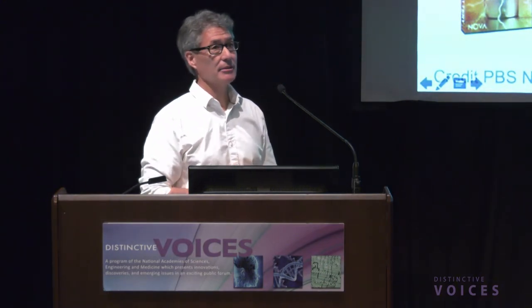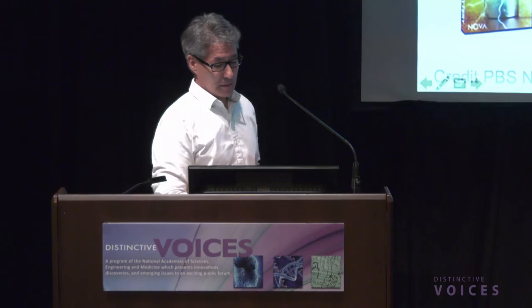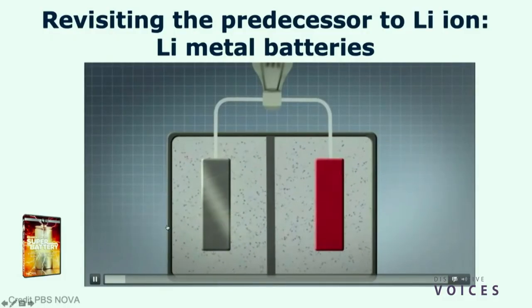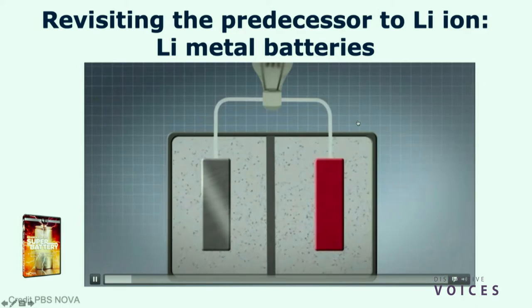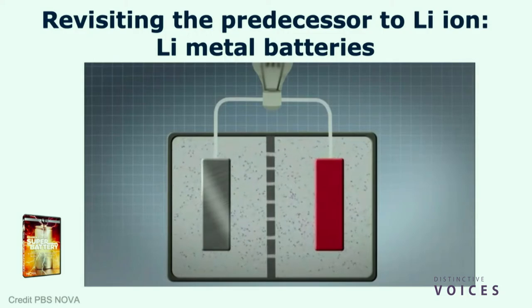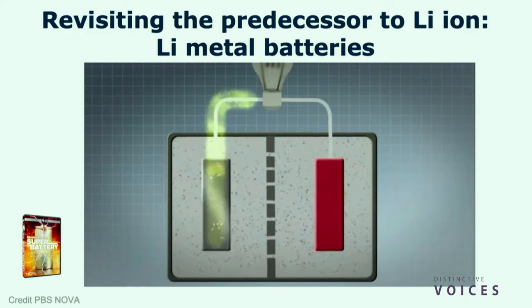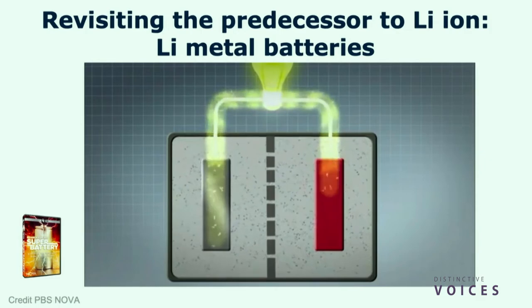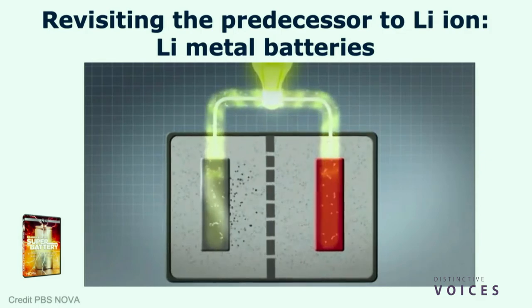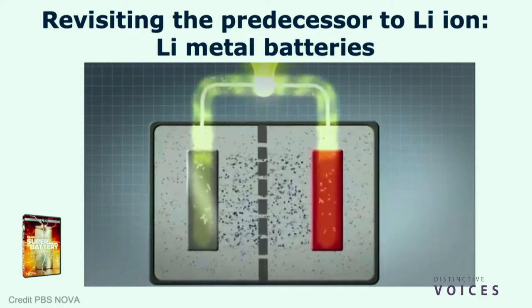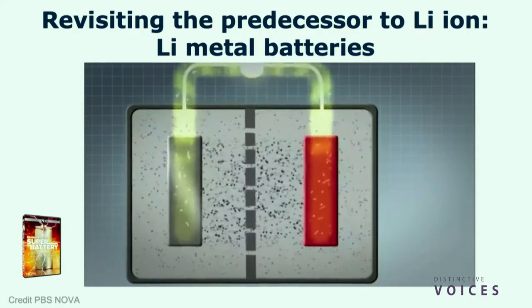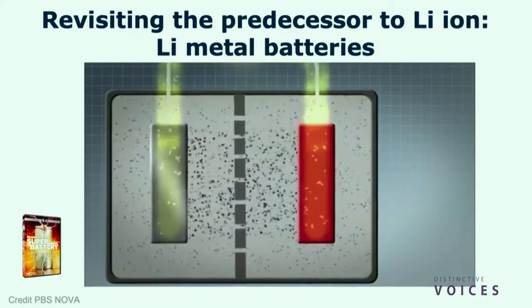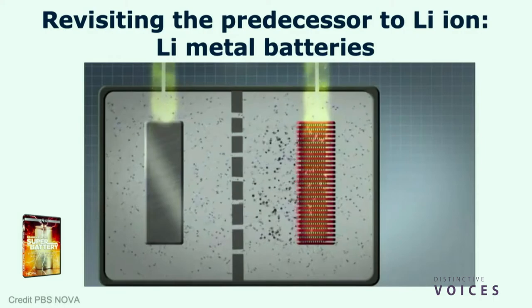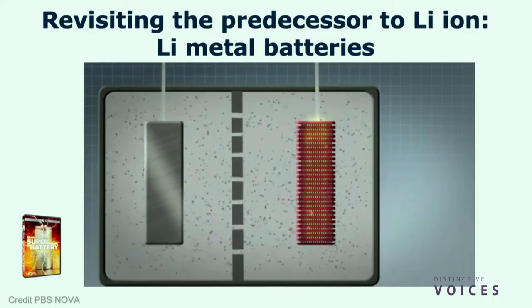So if you look at a lithium metal battery with a liquid electrolyte, so that's taking out the graphite electrode, putting in a lithium metal electrode, liquid electrolyte, lithium ion swimming around, the red electrode is the cathode. And so when you go to discharge a lithium metal battery, lithium ions are stripped from the lithium electrode, electrons go through an external circuit to power a cell phone, and then inside the cell, lithium ions start to fill into that parking structure type architecture that I was mentioning. No problem. Discharge was no problem at all, filling up the parking structure, discharge all the way, get all that energy out of that pure lithium electrode.